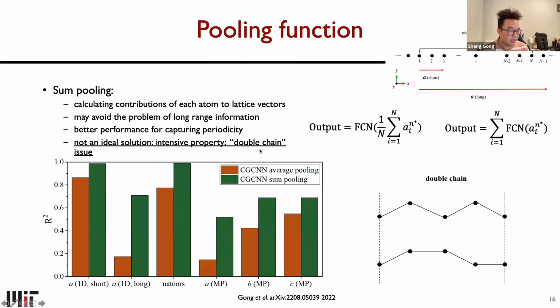For example, we can design the toy case of a double chain. And if we mix a single chain, as illustrated above, with this double chain, we can imagine that sum pooling cannot capture the periodicity well, because we can see that these double chains have similar periodicity to each single chain, but the number of atoms in these structures doubles. So this can easily fool sum pooling for capturing periodicity correctly. And also, I think it might be important for people to have a more formal mathematical analysis about this issue.